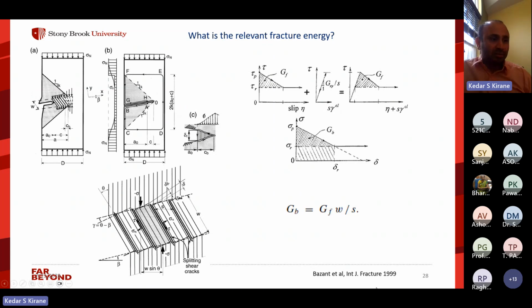But there was some work done by, again, Professor Bazant in the 90s, where he theoretically showed that you can relate the fracture energy associated with the kink band, we call that GB, to the mode 2 fracture energy GF through this expression, where W is the width of the kink band and S is the spacing of these tiny cracks which form axially within the kink band, and they're driven by shear. So in our model, the cylindrical model, we exactly have these kind of axial cracks. Of course, we don't have the spacing. It is all smeared at one material point. But our model is essentially based on this idea.